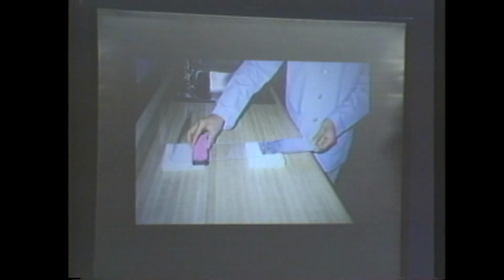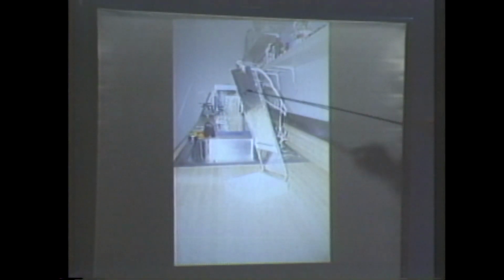Static was generated using a white pine block, which was wrapped in taffeta rayon fabric. To generate the static, I rubbed the long arm of the inclined plexiglass plate with the taffeta rubbing block 15 times. The plate was then turned upright, and the aluminum foil was allowed to cling to the surface of the plexiglass. The time between this point and this point, where the aluminum foil is hanging freely, was measured and recorded.